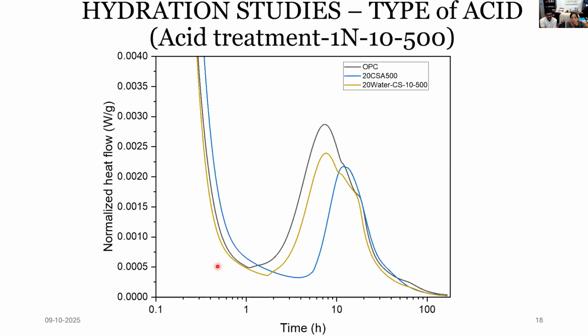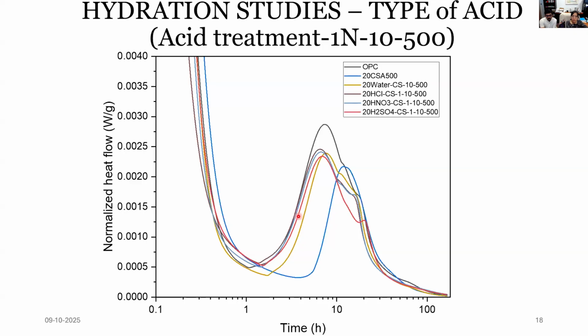In the next slide, we'll see how the different types of acid affect the heat of the hydration reaction in the system. So when we used the cornstover ash, which is treated with hydrochloric acid of 1 normality, we could see that the heat release gets enhanced, and also the dormant period is almost similar to what we see for the original cement. And similarly, when we use nitric acid and sulfuric acid, the pattern is almost similar to the OPC. However, when we see the ash which is treated with sulfuric acid, we could see very clearly that the sulfate depletion peak of the system shifts to the right side.